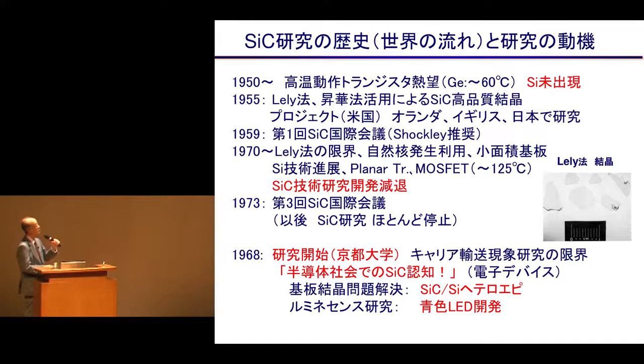And also, the transistor was made available from the latter half of the 70s and for IC. And also, operating temperature could be elevated to 125 degrees. So there was a big progress from 60 degrees to 125 degrees. And so there was much focus or interest in silicon, and silicon carbide was now forgotten. And it's as long as 45 years ago that I was interested in this material.